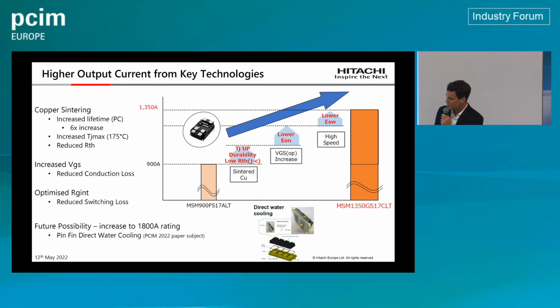It also allows us to increase the maximum junction temperature of the device, operating up to 175 degrees, formerly 150 degrees. And it gives us some small improvement in the thermal impedance from chip to heat sink, which also helps.